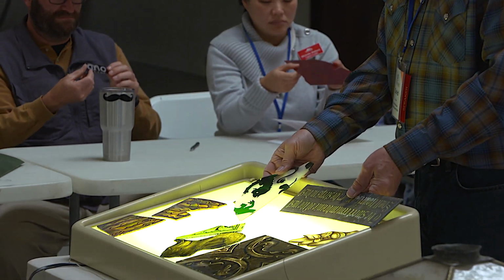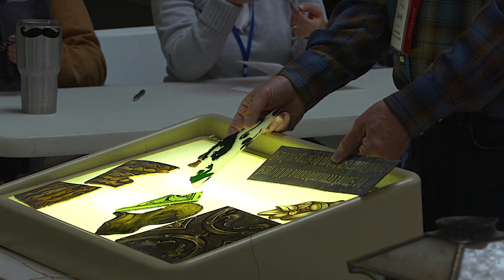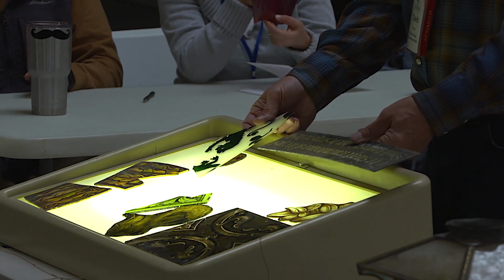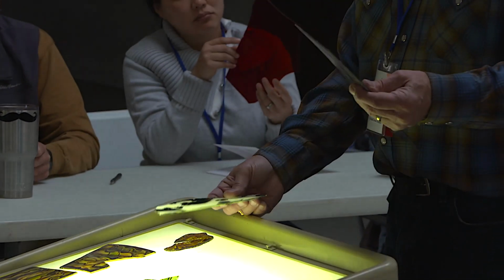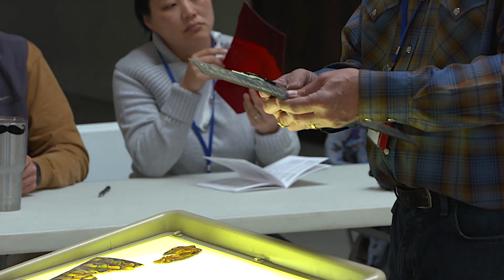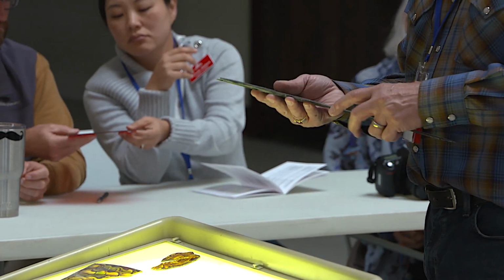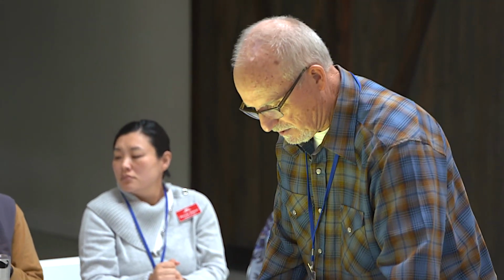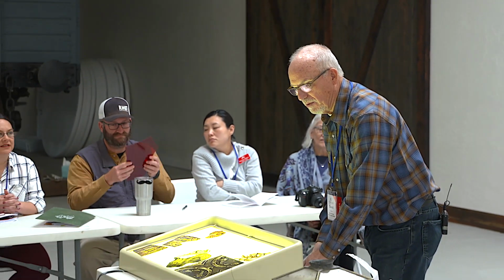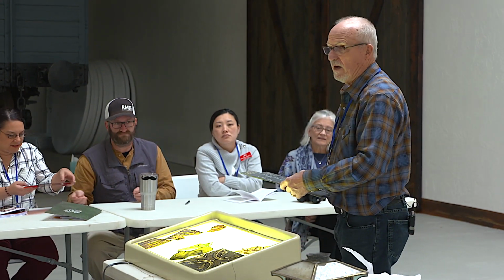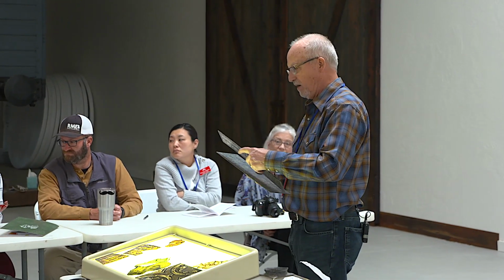Flash glass is pretty rare because it has to be made by a studio that blows glass, not a studio that rolls glass. There is a studio in Seattle called Fremont, because they're in the Fremont neighborhood. Jim, I forget his last name, blows huge bubbles. He can make a bubble this long and about that big around, and then slit it and open it up into a sheet of glass. That's the type of glass that emulates and looks like medieval blown glass. And that red glass, the red flash glass, is a blown glass. So you can see it's very transparent.